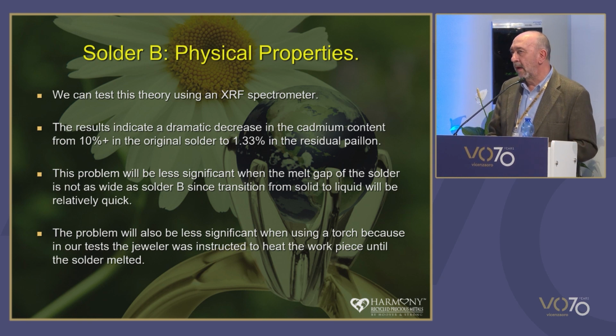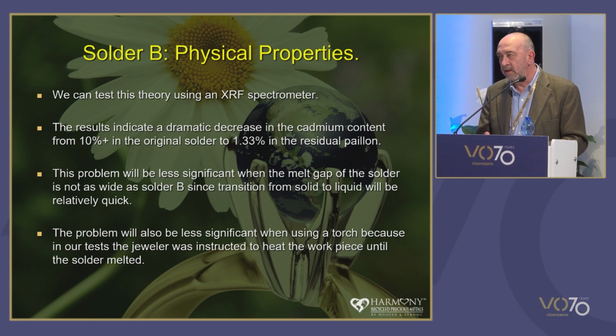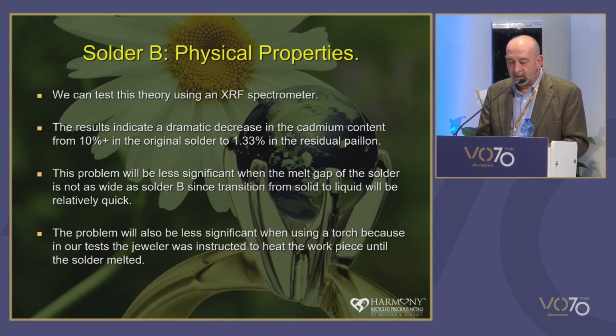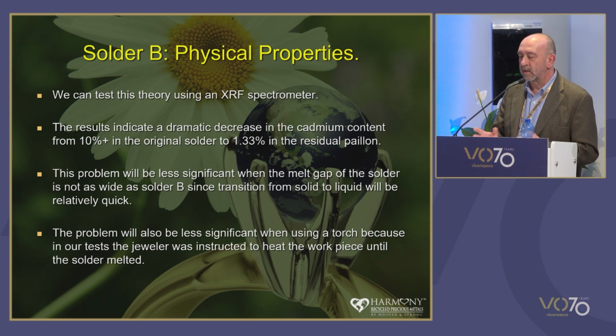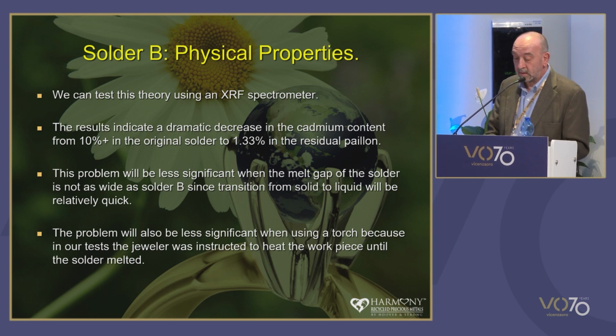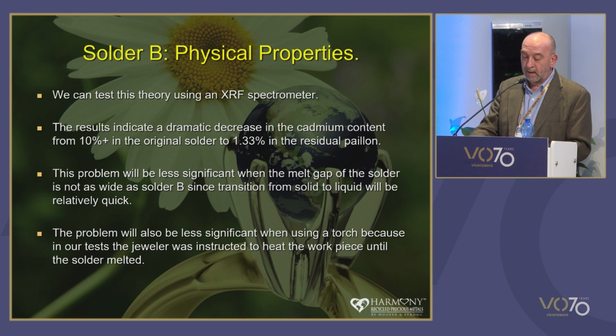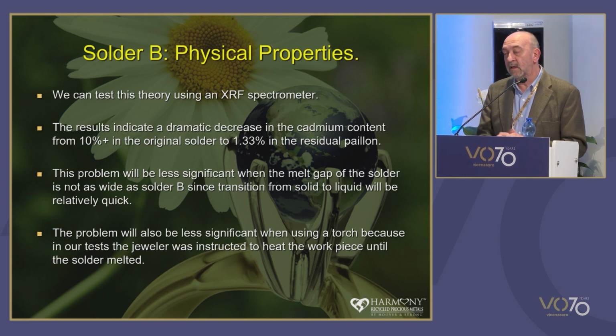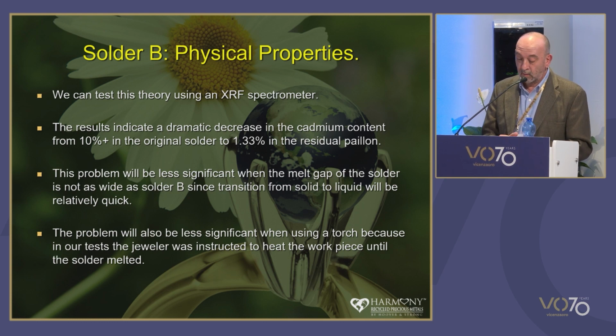And the problem is going to be less significant when the bench jeweler is using it for torch soldering, because in our case in particular, we instructed the jeweler to heat the workpiece until all the solder had melted. So all the solder's going to melt. So what else did it show us? Well, it indicates that if the liquidus of an alloy is lower than the solidus of the alloy to be joined, and the melt gap is sufficiently narrow, and provided the chemical requirements for wetting are fulfilled, any alloy should successfully join any other alloy.